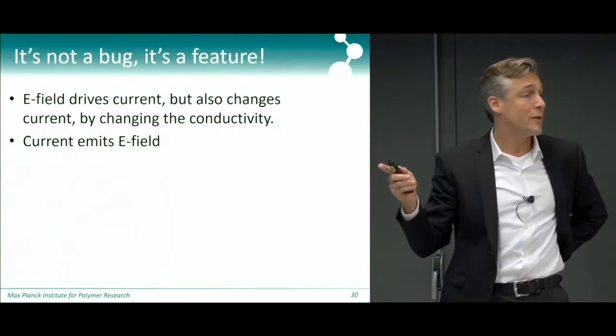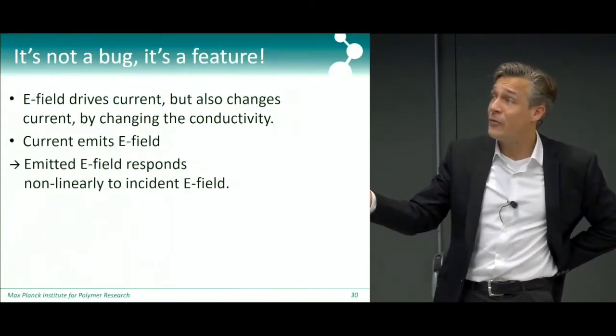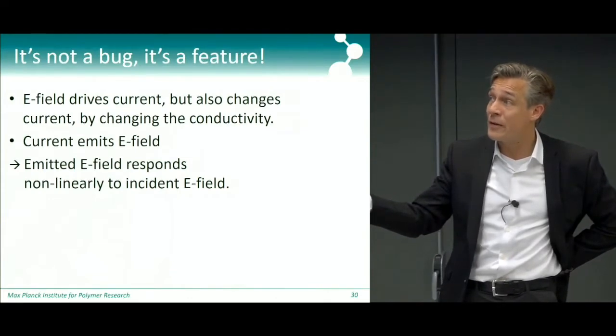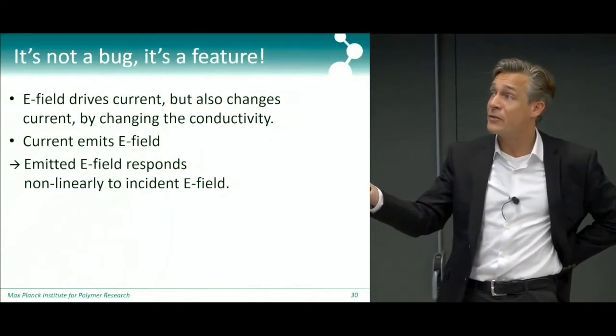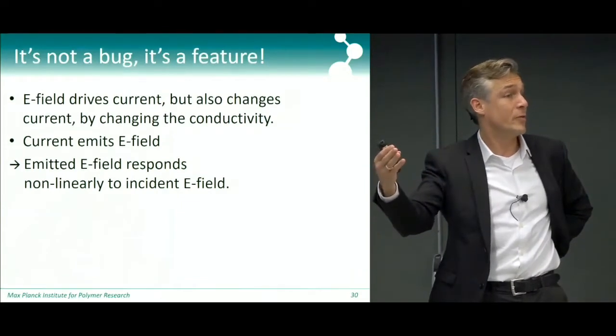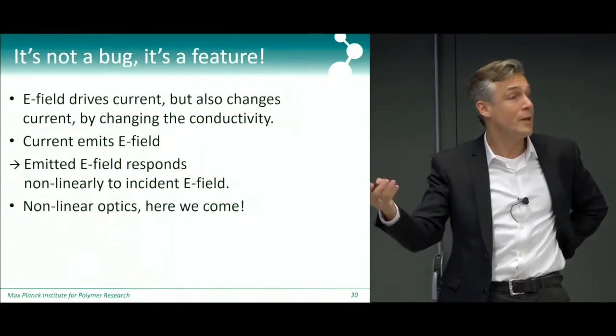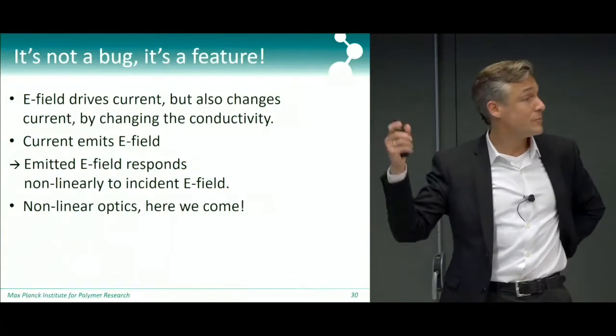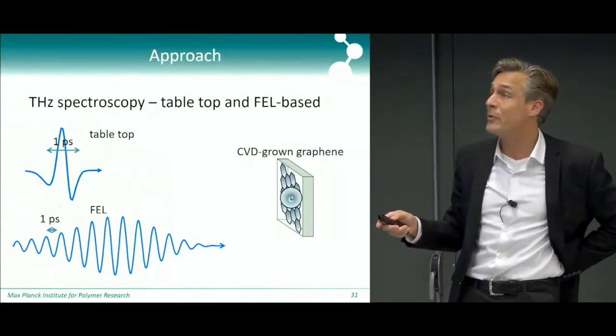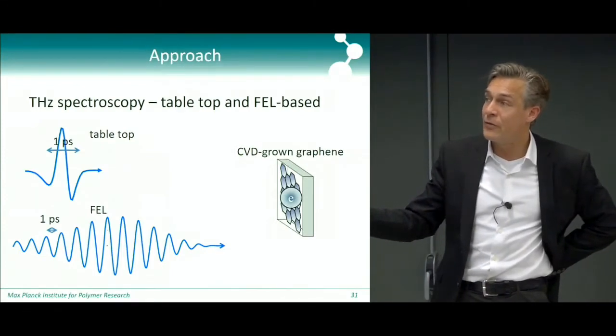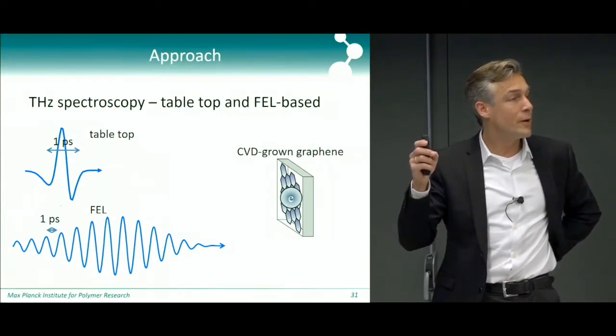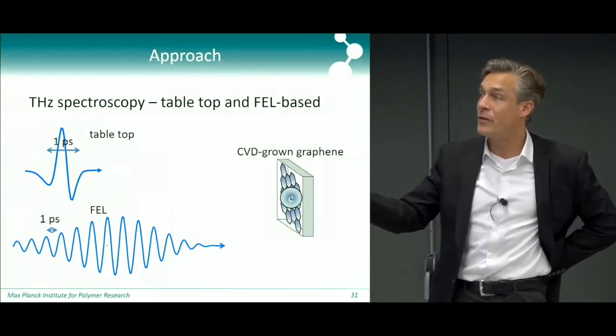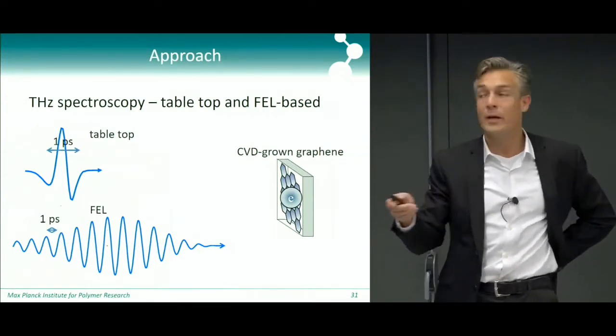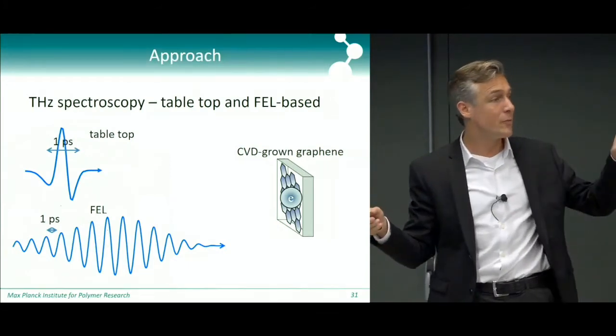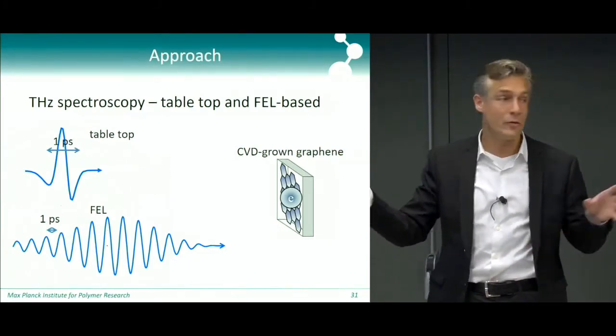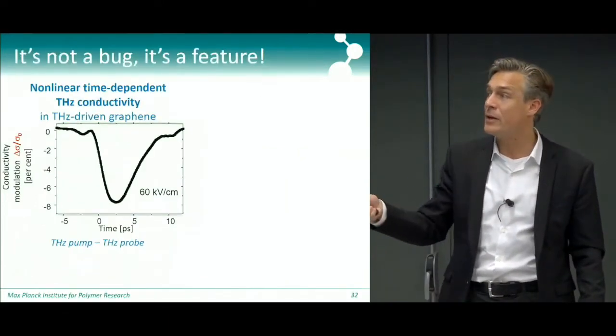This current emits an electric field, but if the system responds very nonlinearly to the incident E field, then this emitted field will contain harmonics of the fundamental. This is a very nonlinear system in essence. And so nonlinear optics, here we come. This is a great system to do nonlinear optics. And so this is why we went to the free electron laser, because if we're going to look at harmonics that are being generated in the graphene, we need a good narrow spectrum. And this has a very broad bandwidth, so it's relatively difficult to distinguish the fundamental from the higher order terms. And here it's very easy.